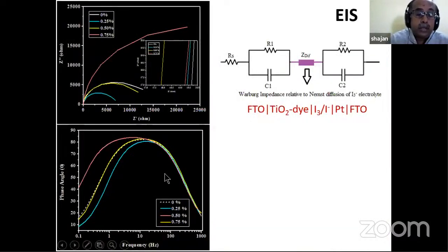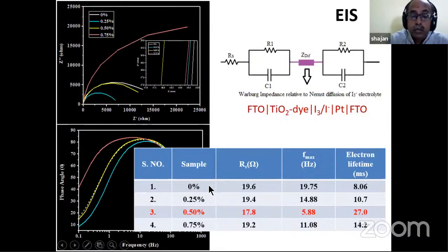And this is what is being recorded. This is the impedance spectra, and this is the Bode plot. You can see at a close look that the resistance is decreasing. For 0.5 percent of MOF, the interfacial resistance is decreasing. And in the Bode plots, you can have the values here. For aerogel, it is 19.6 ohms is the resistance, but when you come to 0.5, it is 17.8. So 0.5% of MOF nickel BTC added to the aerogel is the most favorable condition for solar cells in our findings.